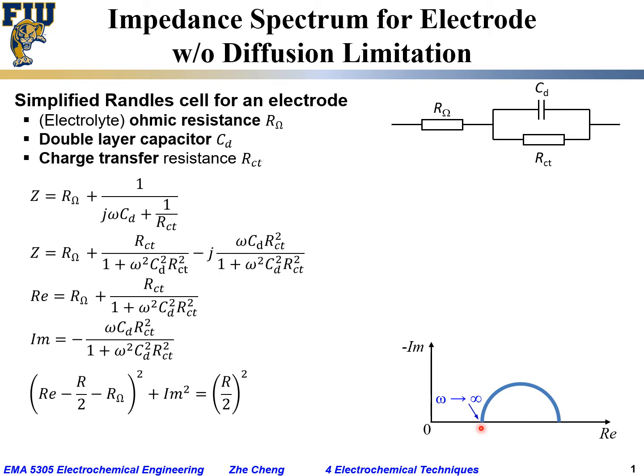And as we learned before, when the radio frequency omega goes towards infinity, which means extremely high frequency, look at here, the denominator becomes infinity and this whole fraction becomes zero. So we would be here, at R_ohm. And for the imaginary part, when omega goes towards infinity, the denominator is omega squared times this one, the numerator is omega, so it comes to be 1 over omega, which becomes 0. So when omega goes towards infinity, we will be at this high frequency intercept. That will be our R_ohm, the ohmic resistance, which means the distance from here to here will give us the so-called ohmic resistance for this Randles cell.